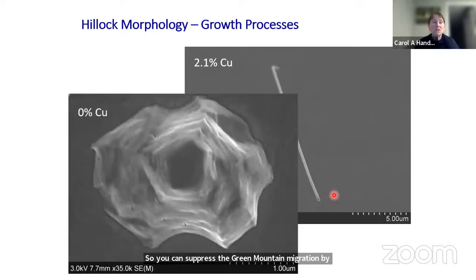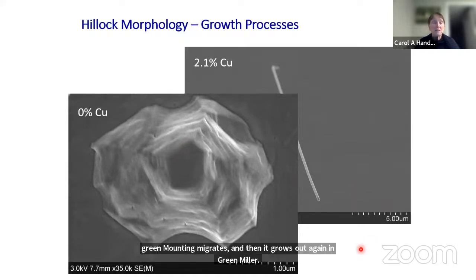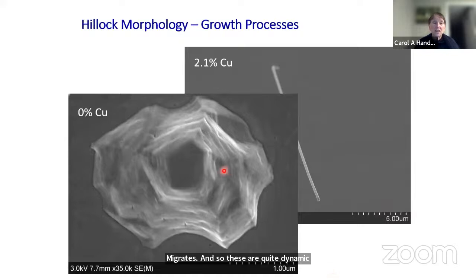This is one with zero copper in it. So the grain boundaries were not pinned. And again, you can see this is the pattern over time. So we've done in situ experiments with this where the grain will grow out for a while, then the grain boundary migrates, and then it grows out again and the grain boundary migrates. And so these are quite dynamic changes. You can see here this is where the triple junction was as a function of time, from here down to here.